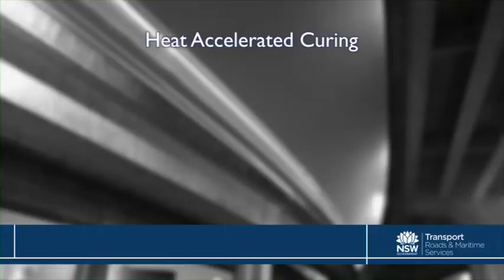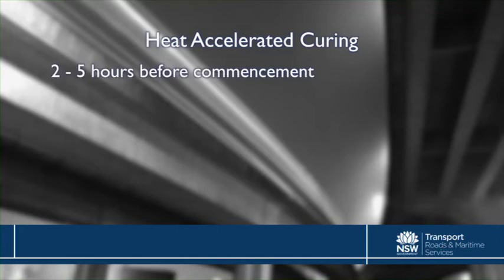Heat accelerated curing seems to be a high risk item. Let's run through the principles of that. Well, the concrete needs to be allowed to gain some strength before commencing of the curing regime, and hence there needs to be a minimum 2 hours before commencement of steam curing or heat accelerated curing, or the maturity must be 50 degrees C hours, but a maximum of 5 hours.